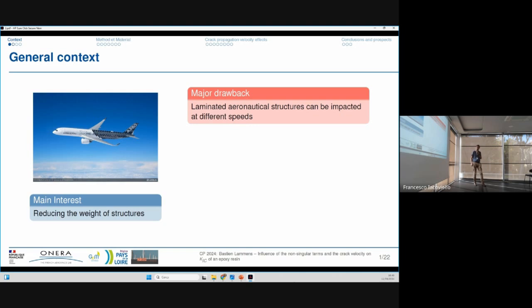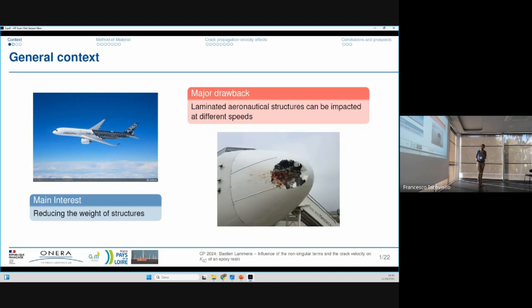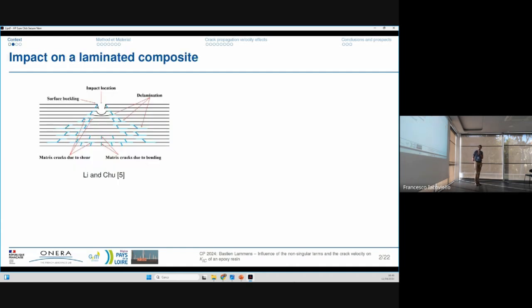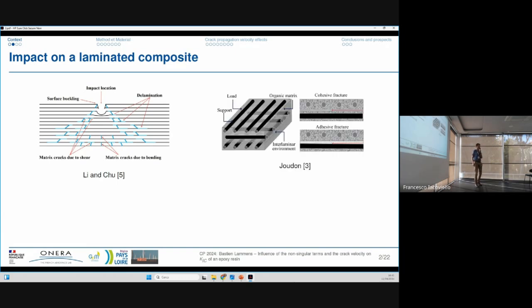But this type of material can be impacted at different speeds, which can destroy the structure, as we can see here with a bird strike. Indeed, when the composite material is impacted, there are different fracture mechanisms. We can mention matrix crack, fiber crack, or delamination. Delamination is the decohesion of the interlaminar environment, which can lead to the destruction of the structure.